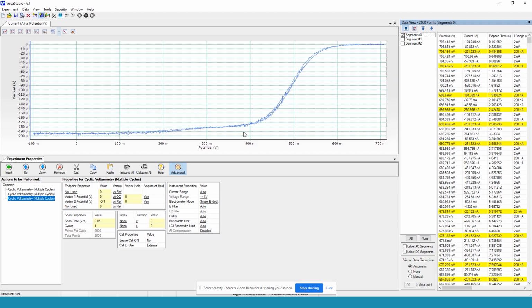The reason for this is that we already explained that the formation of a peak is due to the formation of a diffusion layer that will grow over time. Now, as we are rotating the electrodes, the diffusion layer will actually no longer grow over time because we are actively pushing the active material towards the electrode surface. This will cause the diffusion layer to be a constant thickness, and the replenishment of the active material will no longer change with time. So because of this, we see that the current we measure is also stable over time. So that's why we call these experiments also steady state experiments.